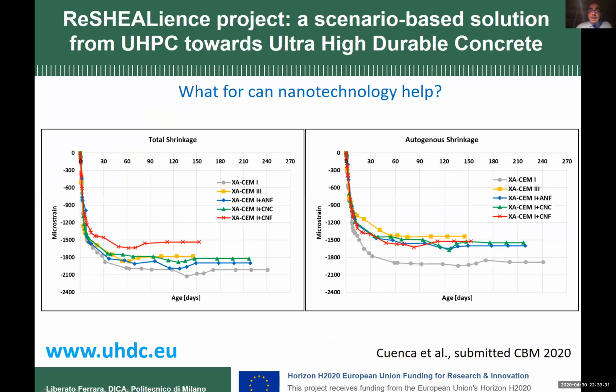Also, this resulted in a reduction of the shrinkage. This reduction of shrinkage lasted - we tested up to more than 6 months - and it is maintained constant over time. And we see here some micro and nano pictures.